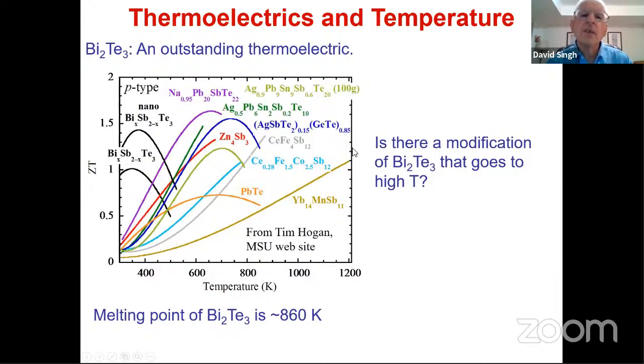What you'll notice is there are many different thermoelectric materials. But if you just look at this chart, for most of them the ZT increases with temperature, reaches a maximum near the maximum temperature for the measurement, and then falls down. This maximum temperature is controlled by the stability of the materials. So going to higher temperature helps ZT, and T is inside ZT, so that may not be so surprising, except for bismuth telluride. For bismuth telluride, the ZT reaches a maximum a little bit above room temperature, and then falls, even though the melting point of bismuth telluride is somewhere here.